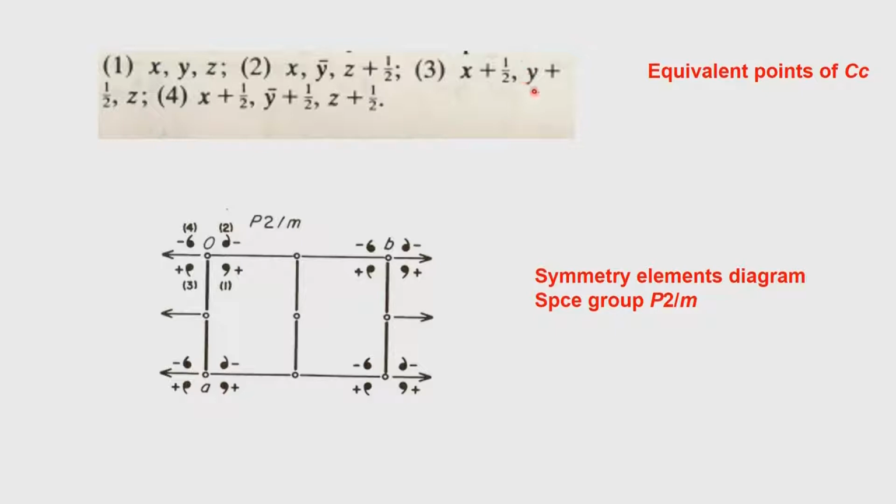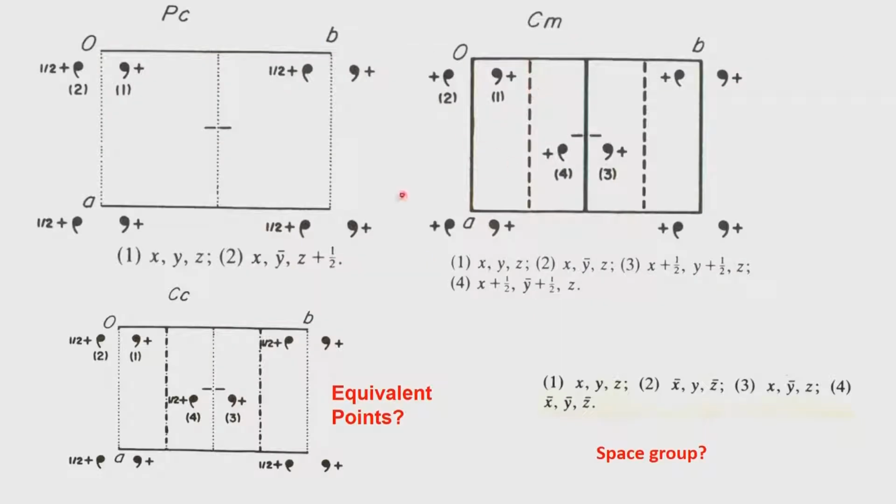So this now brings us to the understanding of 2 of the symmetry elements. In fact, today we have seen the CC, the presence of the mirror point group symmetry. We have also seen the presence of 2 as well as a perpendicular mirror. So this space group analysis now tells us that we are now looking into a center of inversion related space group. All the earlier space groups PC, CM, CC belong to the non-center symmetric space groups.